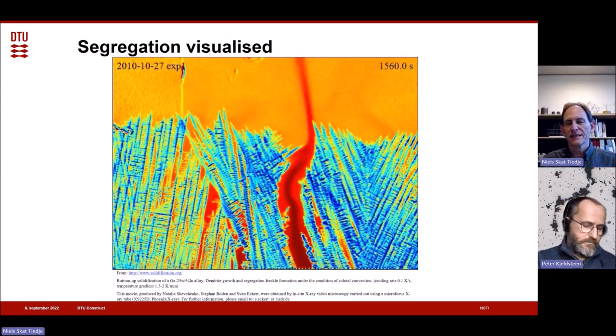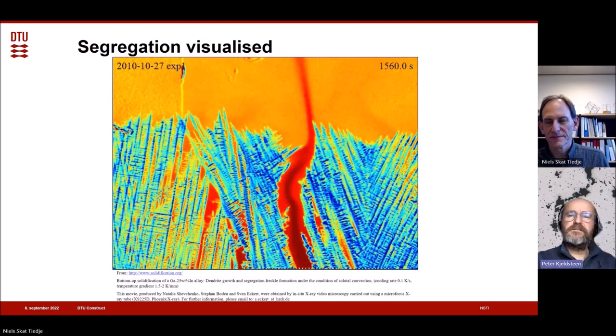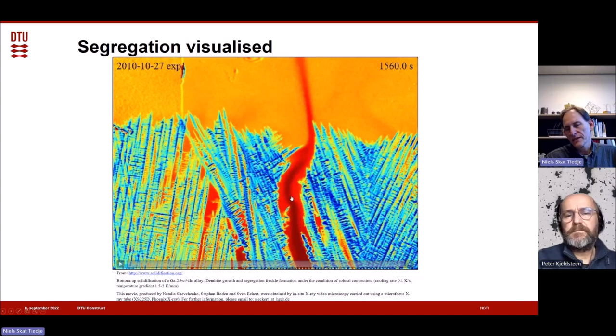It's very, very impressive. I've seen it in my master's project. It comes from 6 meters height and you have 100 tons of liquid steel that suddenly, like a shower, comes out all over the place. Burst out, yes. So, very impressive, but a little bit dangerous. So is it called a hot tear when it breaks open? Well, in this case, it will be a hot tear. In steel production, they call it breakouts, because you basically have a solid shell with liquid inside it. And when that solid shell bursts, it is somehow cool, but it's not so good for the steelworks.